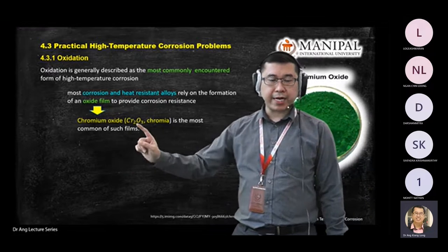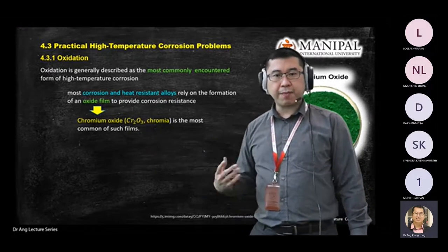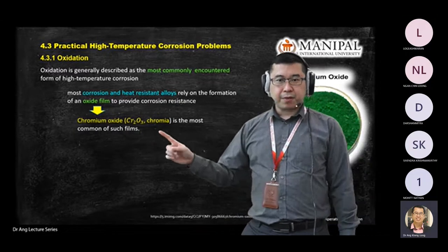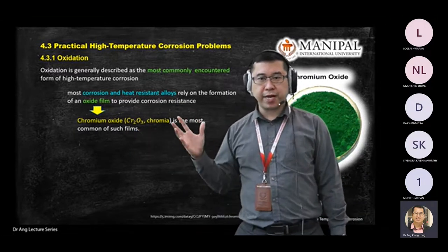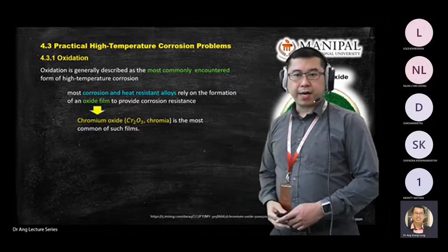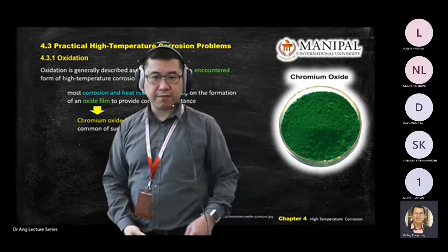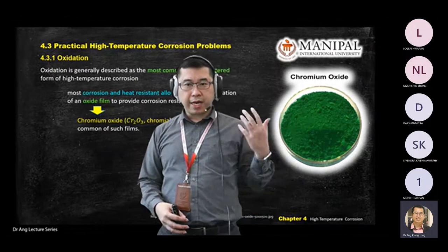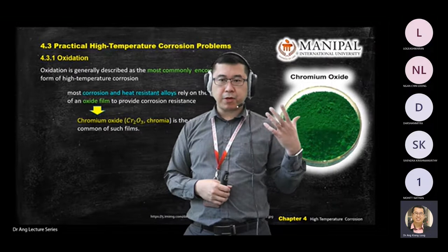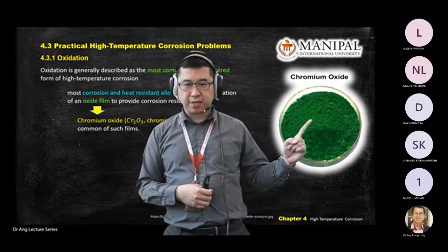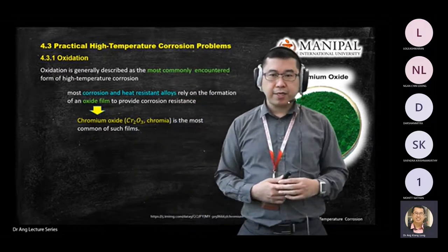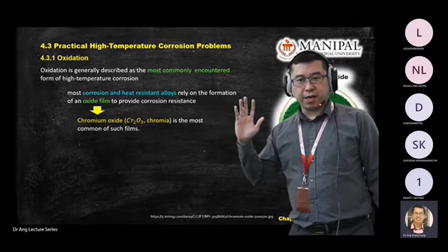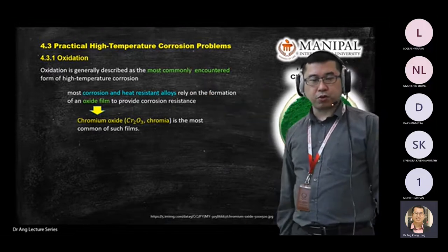In the raw form, if you go to a chemical lab and request chromium oxide, they are in green color. Just to give you a visual aid — under corrosion, this will be the color you see under high temperature corrosion. How do you know that you're having a chromium oxide? You take the high temperature corrosion sample or a device that broke down under high temperature operation, then you cut it and do a cross section. You can see that there's a layer of green color at the rupture area — at the section that broke down.